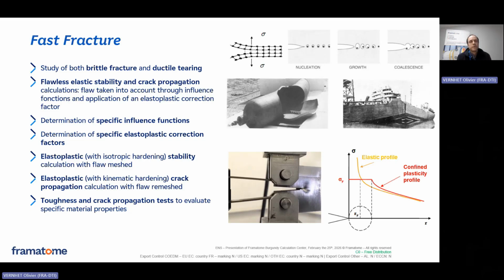So we mesh the flaw. I provided you just a few slides before an example of a mesh with a flaw model. This is a typical calculation we perform. We model the flaw, we put in some elastoplastic material properties and try to check that the defect is stable. We might also perform some elastoplastic crack propagation analysis with a flaw that is remeshed along the propagation. And once again, we might perform some toughness and crack propagation tests, also at the technical center just beside.